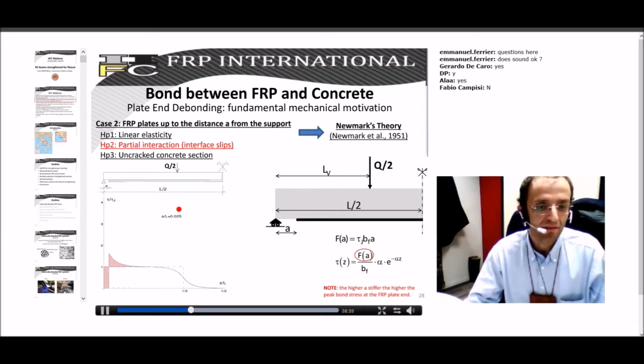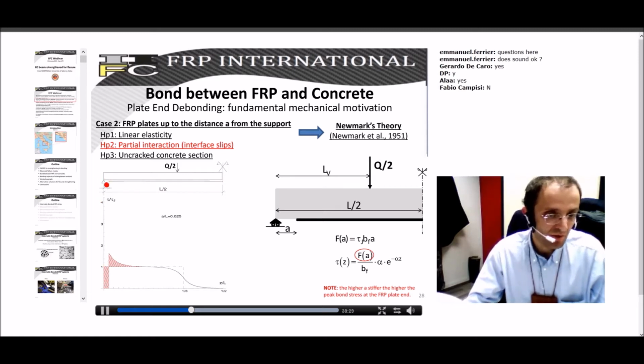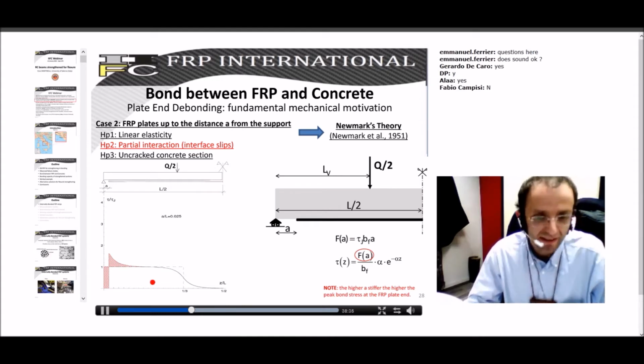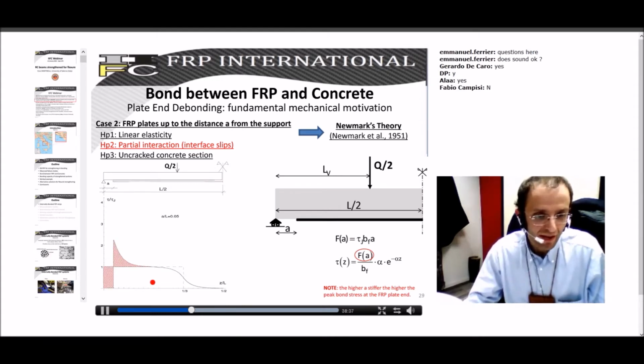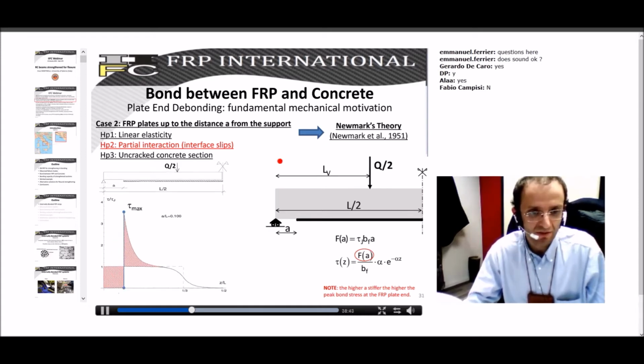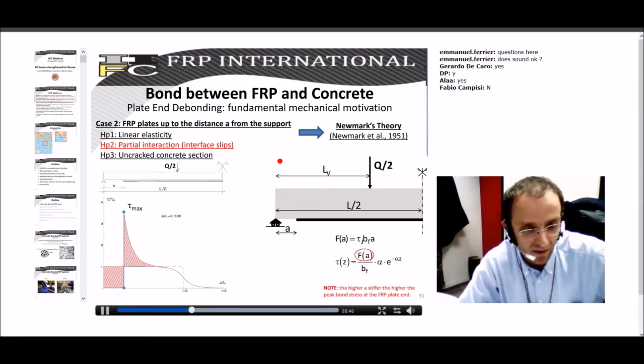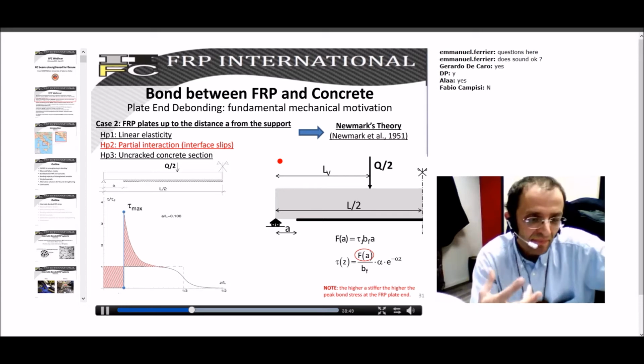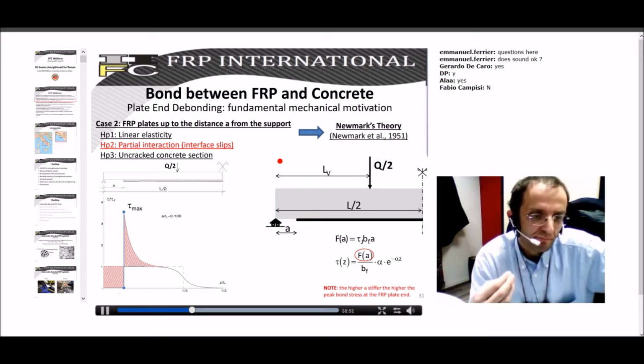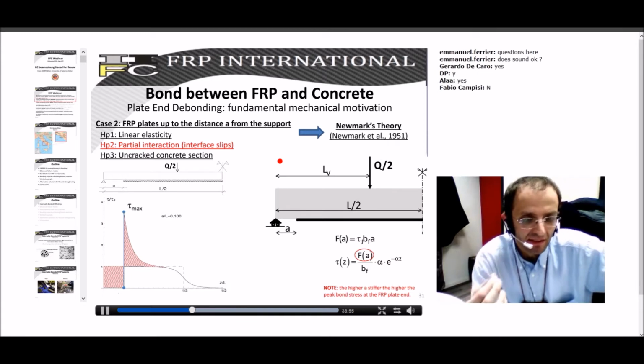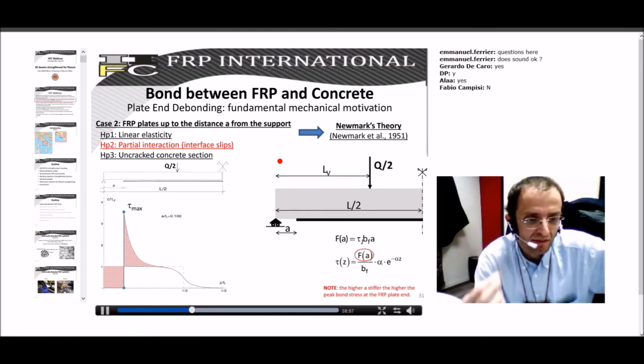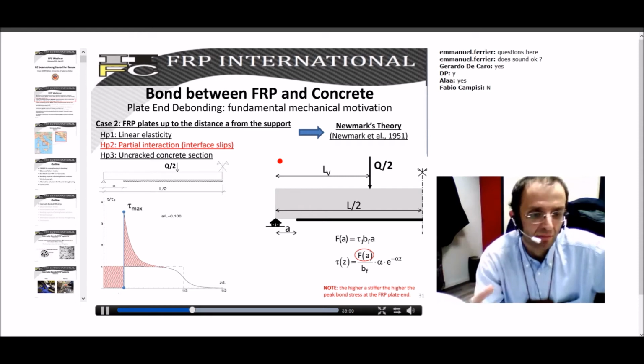Then, if you have a cutoff section, this part of the bond stress, which is not actually present because there is no interface, is now concentrated here, and this peak is as sharp as alpha is high. So for a longer distance, you have a sharper peak, and so on, up to getting a certain tau maximum. So as you see, if we accept the assumption of elastic material, this is the distribution of interface shear, bond shear stresses.